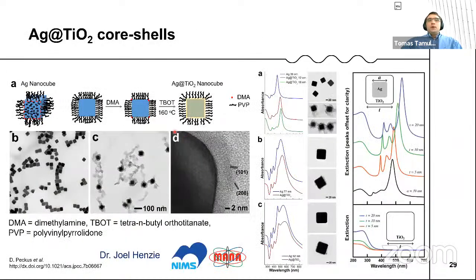And together with our colleagues, we have investigated nanoparticles that are like core shell structures with titania. So you have to do some advanced chemistry to synthesize those, but you can coat and see that this coating is not destroying the plasmonic resonance, and it's according to the simulations.